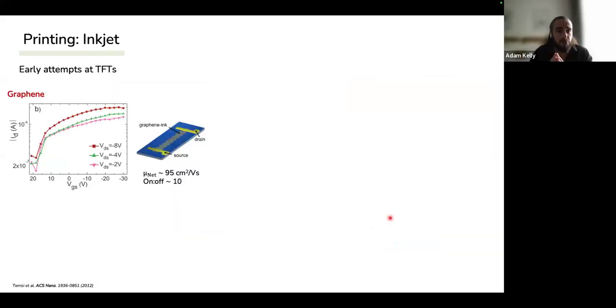So everybody was trying to make transistors, because graphene has high mobility. So the question was back at the beginning, how do we access this? How do we exploit it? So Felice Torrisi in 2012 inkjet printed graphene onto a silicon dioxide wafer. They were able to gate it. Well, I mean, there was an on-off ratio of about 10, which is not bad, I would say, for a zero bandgap semiconductor. And they showed a mobility of about 95.